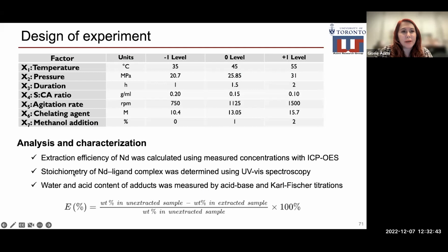Again, we use design of experiment containing 7 parameters: temperature, pressure, duration, solid to chelating agent ratio, agitation rate, chelating agent, and methanol addition. To calculate the extraction efficiency, we measured the composition of the sample before and after SFE, and by subtracting them and dividing by the weight percent of the unextracted sample, we obtained extraction efficiency. The stoichiometry of neodymium ligand complex was determined by UV-visible spectroscopy, and water and acid content of the adduct was measured by acid-base titration and Karl Fischer titration, respectively.